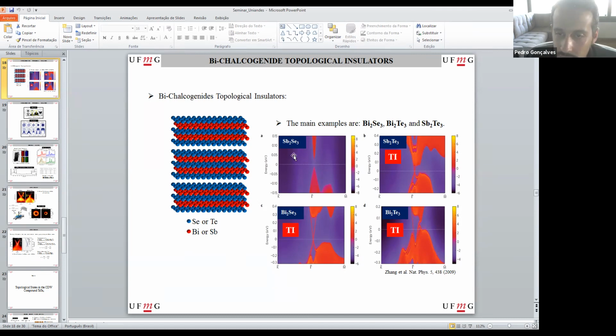So what we observe is that even if you put a lot of antimony on the structure, even if the antimony is equal to the bismuth amount, when we put just a little bit of tellurium, the sample starts to become a topological insulator again. So if you have the same amount of bismuth and antimony, the effect of tellurium is pretty much stronger on the topological insulator behavior. This was kind of expected because in bismuth telluride the state is much more robust than in the bismuth selenide sample.